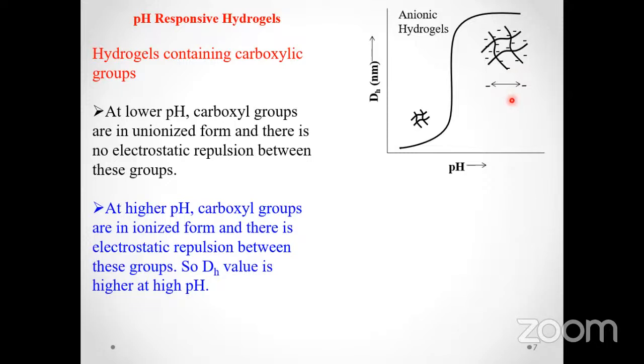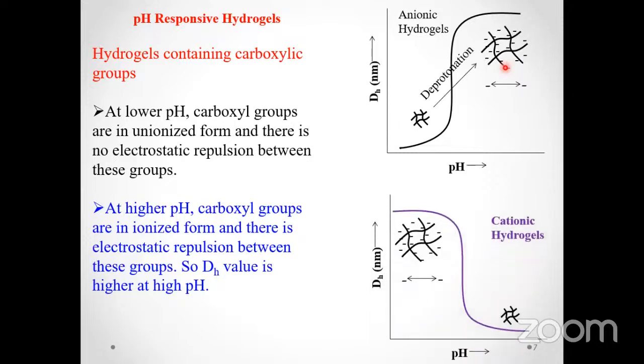When the polymer chains are extended within the hydrogel network, the size of the hydrogel network is increased, which can be seen in this figure: if we have an anionic or acidic hydrogel, then at higher pH value, when the acidic groups are deprotonated, the size of the piece or particle of the hydrogel is increased. Similarly, if we have a basic or cationic hydrogel, then a reverse trend will be observed, and the same chemistry is involved over here as well.